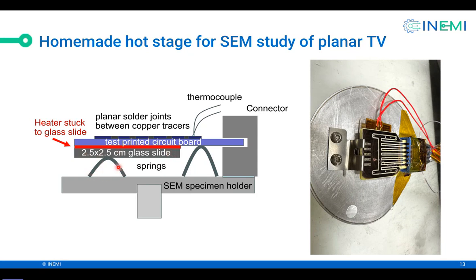So the C-clip pushes the glass slide, which pushes the heater against the circuit board. So you get good thermal contact. And this clip is to ground the solder joint, because in SEM, you have to ground the specimen, otherwise you get electron charging. Now, these two springs are pushing this whole setup up. It's held on the right, but not on the left. So we built a clip with two screws to keep the setup down on the left side also. So right side, it goes into a connector.